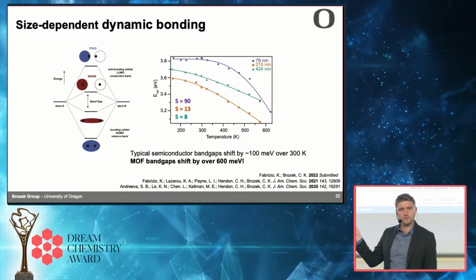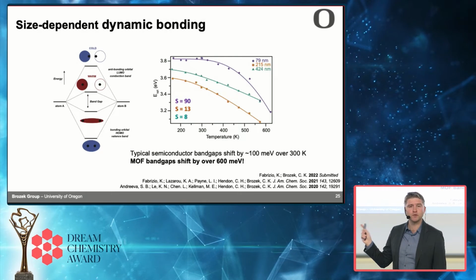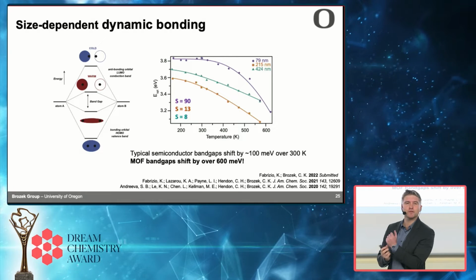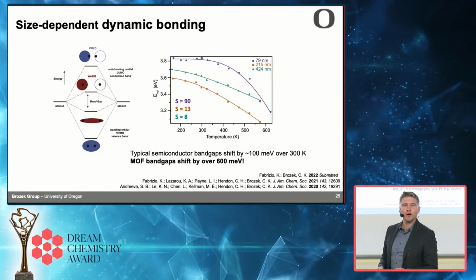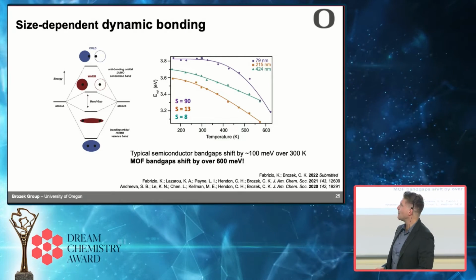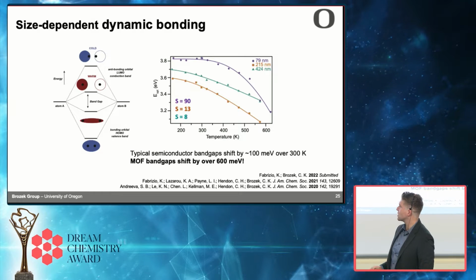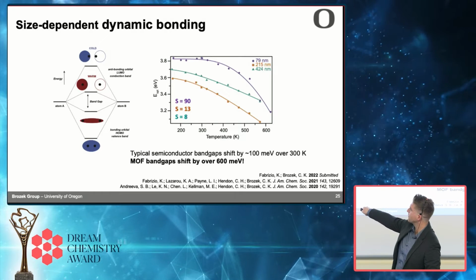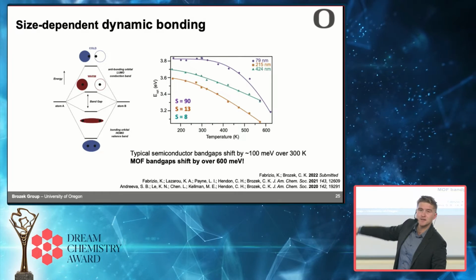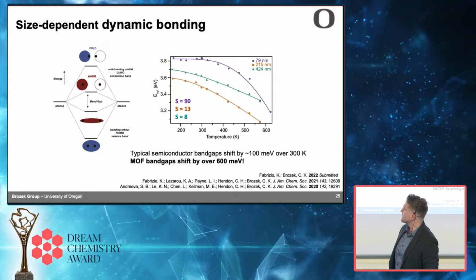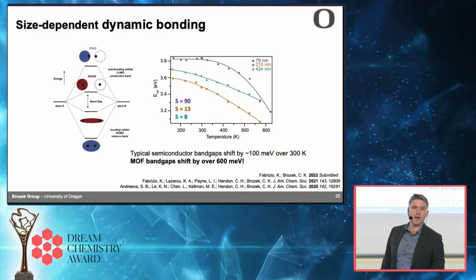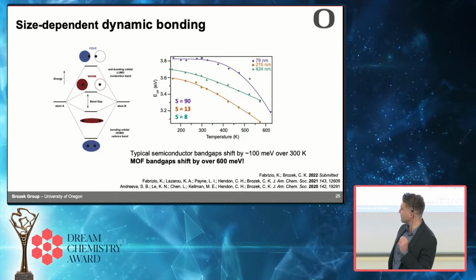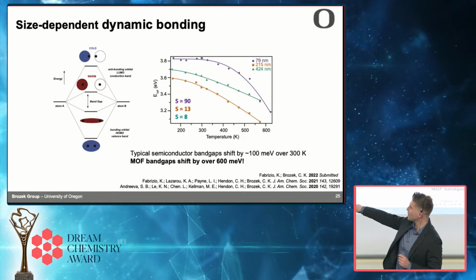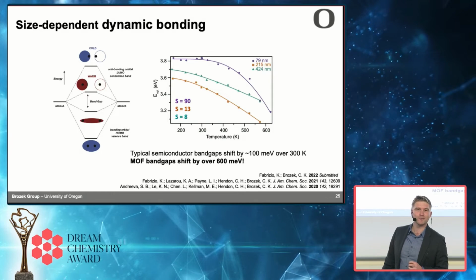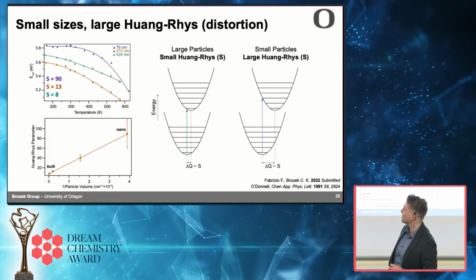We fitted the data to something called the O'Donnell and Chen model. So this behavior was first discovered by someone named Varshni. There's this whole Varshni model, but there's a modified version called the O'Donnell and Chen model. That's what the data is fitted to. And it gives you this S parameter. This S parameter is called the Huang-Rhys parameter. It's a very special thing. But before I explain what it is, just note that it clearly gets bigger for the smaller particles, okay?